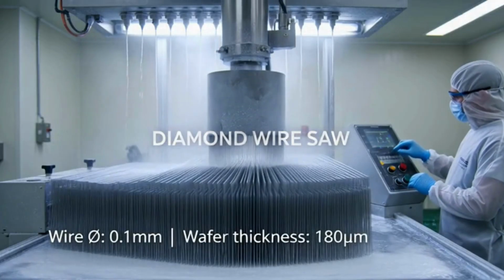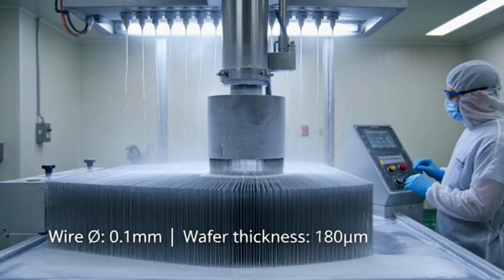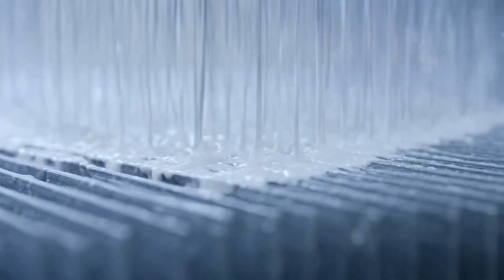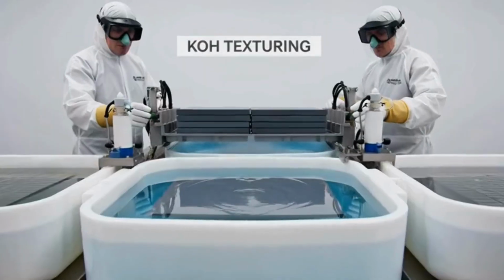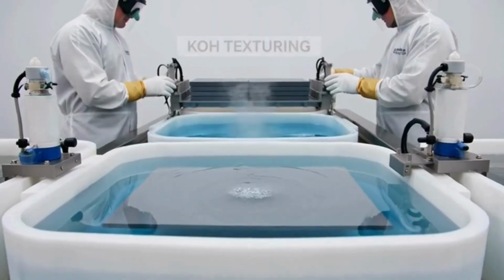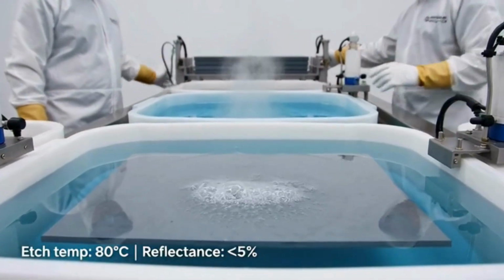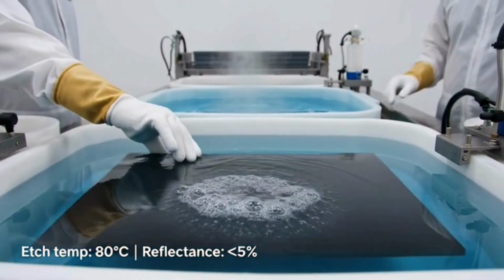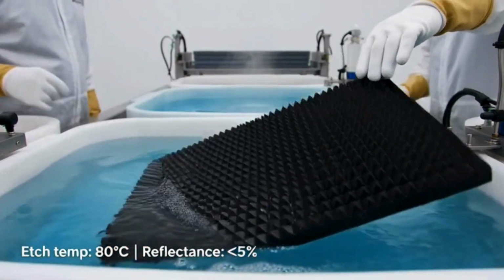A multi-wire diamond saw slices the boule into wafers just 180 micrometers thick. One ingot yields over 1,000 individual silicon wafers. Wafers are etched in alkaline solution, creating microscopic pyramids across their surface. This texture traps incoming light, cutting reflection losses to less than 5%.